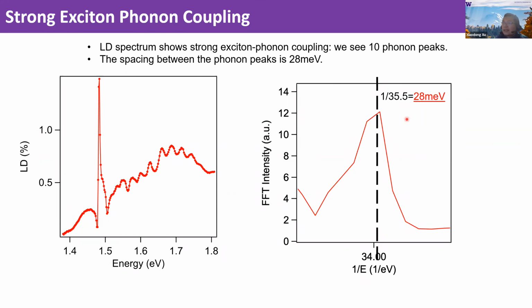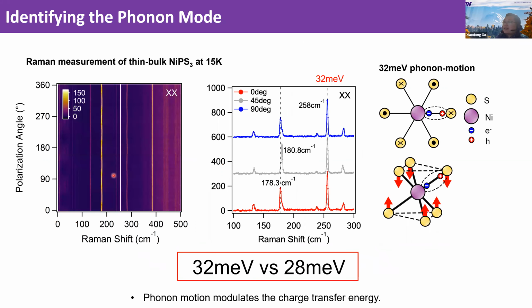Then the second possibility is exciton and phonon coupled together. Therefore, we looked at the Raman spectra of these crystals, and here's our measurement. We don't see any mode at 28 millieV, but we do see a mode at 32 millieV, corresponding to out-of-plane motions of the sulfur atoms. Okay, so it's an A1g phonon. So now this 32 millieV will be a candidate for these exciton phonon bound states. But why is there a difference? Why is it not 32? Why do we see 28?